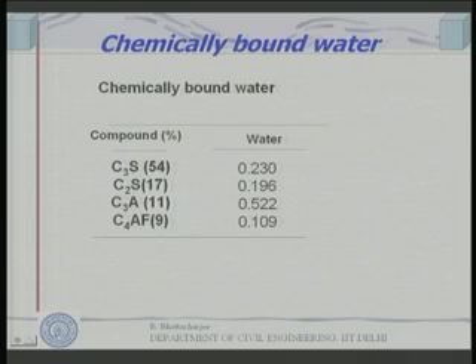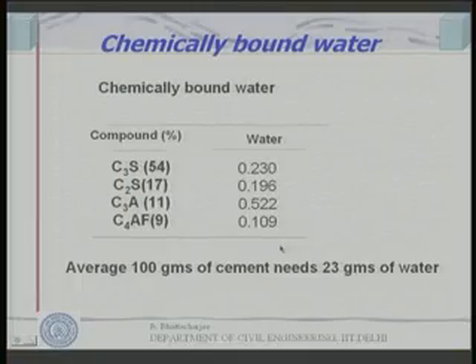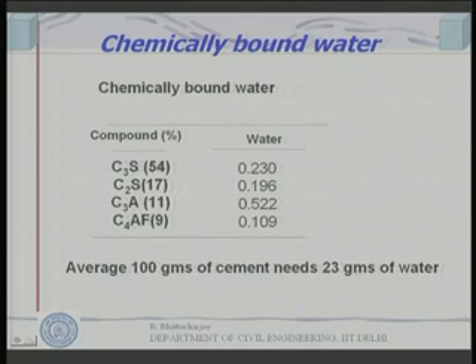And I also know what percentages of these compounds are present in ordinary Portland cement. They are 54% for C3S, C2S is about 17%, C3A is about 11%, and C4AF is about 9%. So, I can find out how many grams of water 1 gram of cement will consume. It is a simple calculation, because it is the law of mixtures, nothing else. Based on that, we can show that 100 grams of cement needs about 23 grams of water. This has been accepted by various experts, and generally it is accepted by concrete technologists that about 100 grams of cement needs 23 grams of water. There can be some variation here and there, since the percentages of C2S and C3S can vary slightly, even in OPC. It is based on one experiment done. So, on average we take it for granted that 100 grams of cement needs about 23 grams of water for complete hydration over a very long period of time.